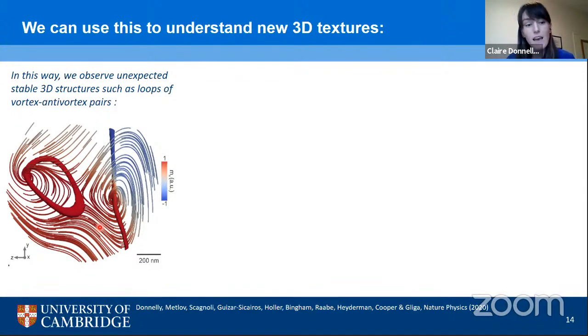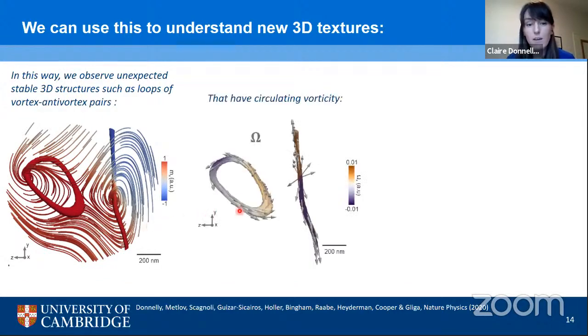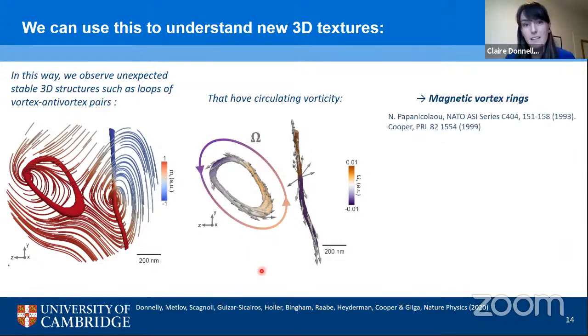However, it wasn't until we plotted the magnetic vorticity vector that we could really see what was going on. Specifically, when we plot the vorticity vector, we see that the vorticity is circulating around this loop, meaning that these are magnetic vortex rings. Magnetic vortex rings were first predicted back in the 90s by Papanikolaou and Nigel Cooper, who is one of the co-authors of this work, but they have not yet been observed directly.